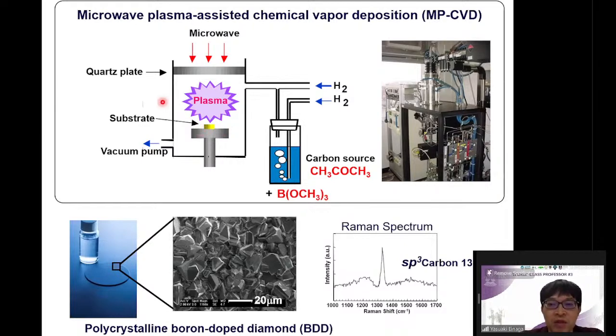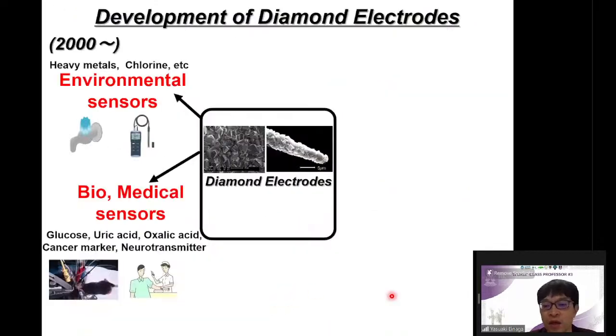We are using a microwave plasma CVD system. By using this microwave plasma, as a carbon source we are using acetone, and trimethoxyboron is the boron source. We can control the concentration, and we can control the conductivity of the diamond. So we are making a highly boron-doped diamond by using this system, and this is a polycrystalline boron-doped diamond.